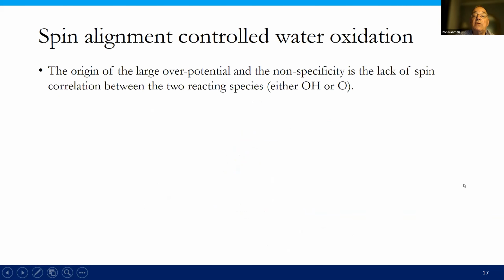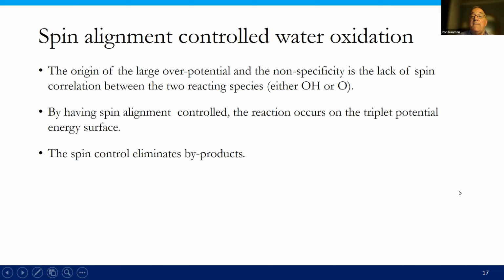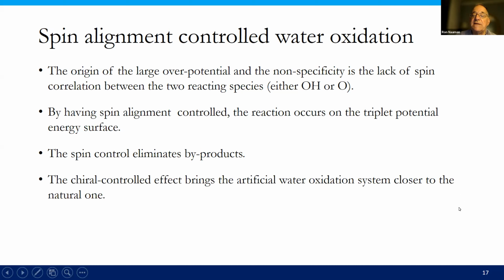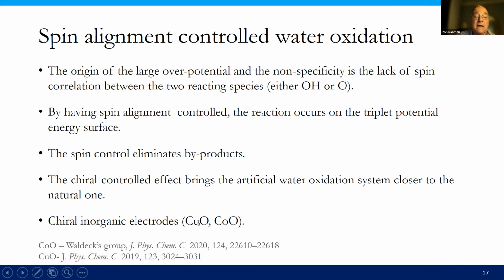So basically what we have here, by controlling the spin, we can make a forbidden reaction go. We reduce the overpotential and we avoid the unwanted byproduct. Basically, we make this artificial process more like the natural process that exists in nature. This can be done not only with chiral molecules, it can be done also with chiral inorganic electrodes, like different oxides, and the group of Waldeck demonstrated some of this work.